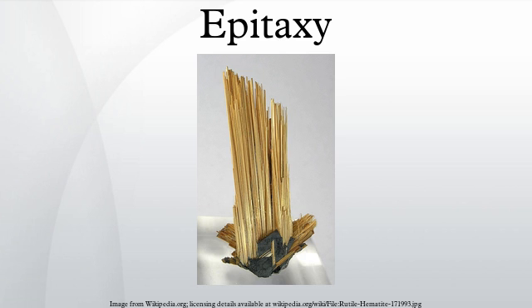Silicon VPE may also use silane, dichlorosilane, and trichlorosilane source gases. For instance, the silane reaction occurs at 650°C: SiH4(g) → Si(s) + 2H2. This reaction does not inadvertently etch the wafer and takes place at lower temperatures than deposition from silicon tetrachloride. However, it will form a polycrystalline film unless tightly controlled, and it allows oxidizing species that leak into the reactor to contaminate the epitaxial layer with unwanted compounds such as silicon dioxide.